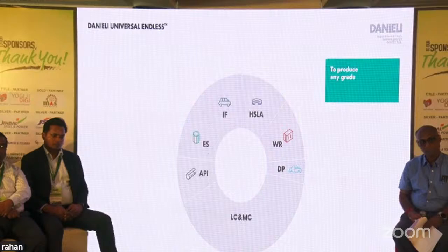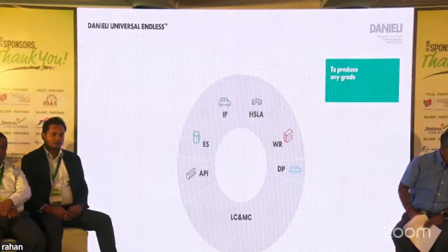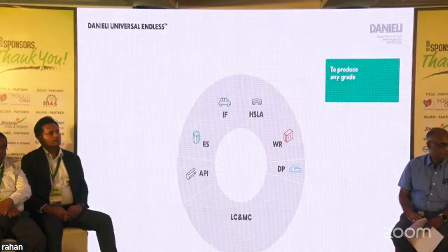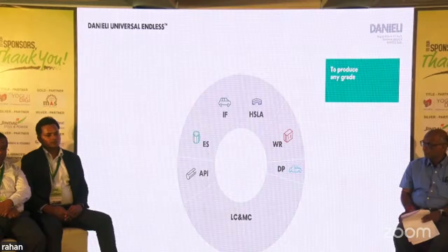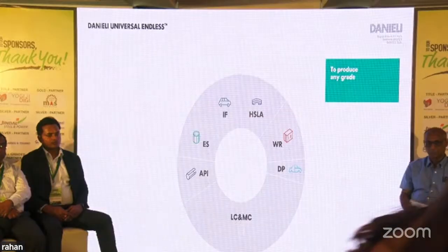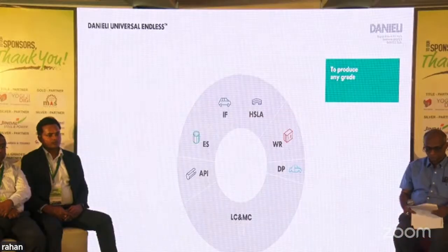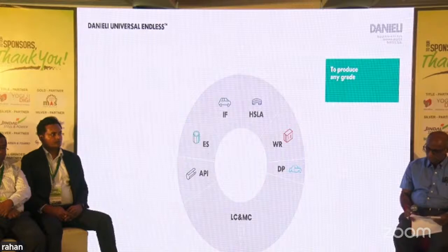ES electrical steel, API up to X80. And how is it possible? Our rougher and finishing stands are separate, and in between them we have a transfer bar cooling. So you can bring the temperature below the recrystallization, and that promotes thermomechanical rolling. For electrical steel, as I mentioned, there are induction heaters before the finishing mill, so you can go with higher input temperature to have around 920 degrees centigrade, which is required at the exit of the FM. So practically you can have all the grades from one single mill.